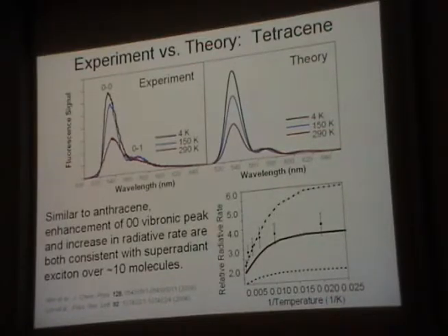The second measurement is the oscillator strength. As you lower the temperature, it shoots up. You start at about twice the oscillator strength of a monomeric tetracene. As you lower the temperature, it goes up. The best fit is roughly a 3x3 aggregate for both cases. Okay, so we can do two independent spectroscopic measurements, and we can sort of figure out what is this state, how big is this state that we're looking at inside the tetracene crystals, or in this case, a polycrystalline film. Okay, so in other words, I'm not just making it up that these states are here. We can quantitatively measure them and characterize everything, right? Their size, their oscillator strength, all those types of things. So that's a nice thing.